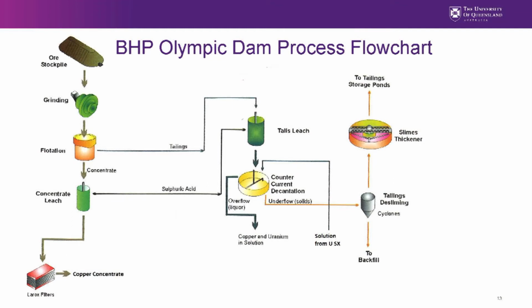So this is a simplified flow sheet of the first section of the Olympic Dam process. So the ore is mined and stockpiled, ground down for flotation. There's a flotation concentrate from this process, goes to what's called a concentrate leach step. It's important here to separate the copper, actually as a main objective, and some of the uranium and thorium are separated in this leach step, and then the dry concentrate proceeds to smelting on site.